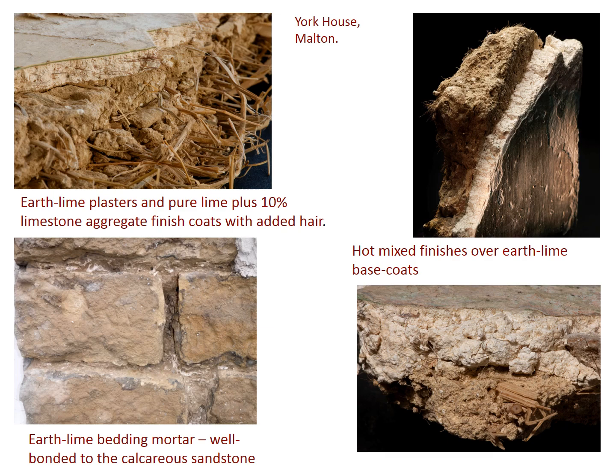Some earth lime mortars, coupled with pure or very nearly pure lime finish coats from Malton and the North Yorkshire area. Here are earth lime plasters with pure lime plus 10% limestone aggregate in the top left, hot mix finishes over earth lime base coats to the right, and still well bonded earth lime bedding mortars to a calcareous sandstone.